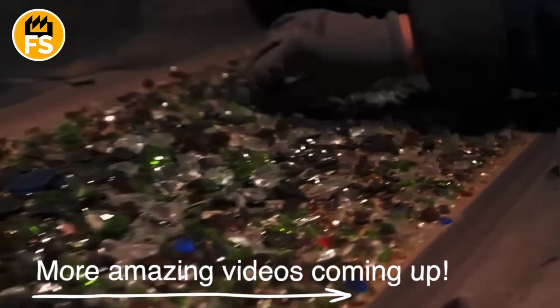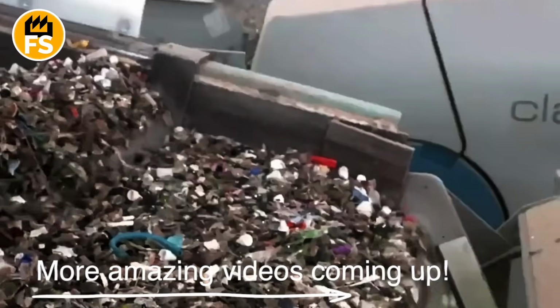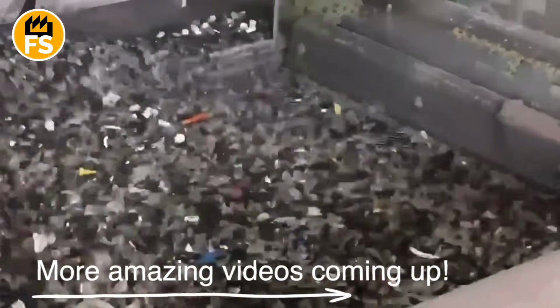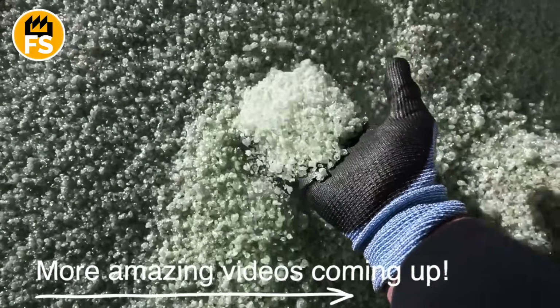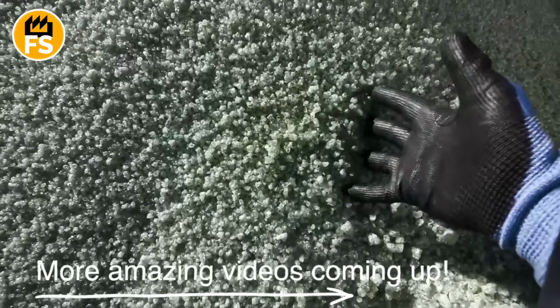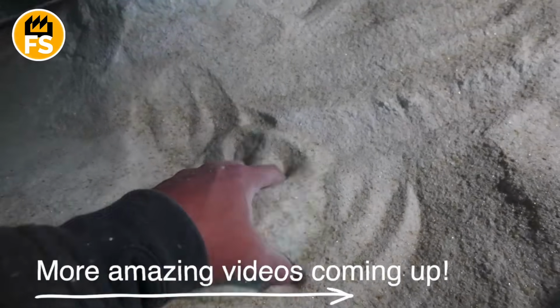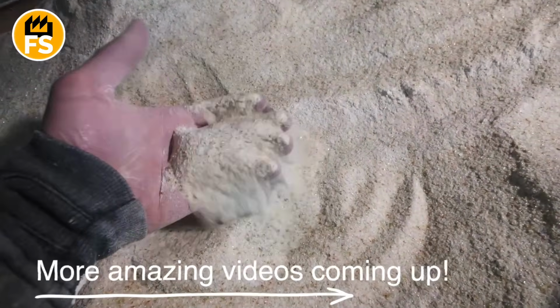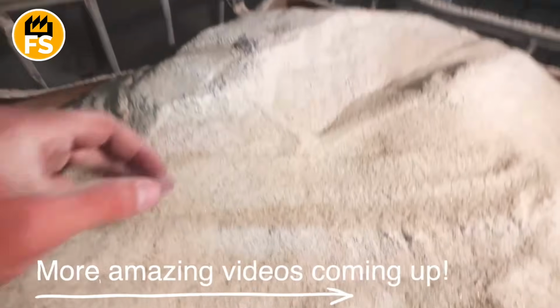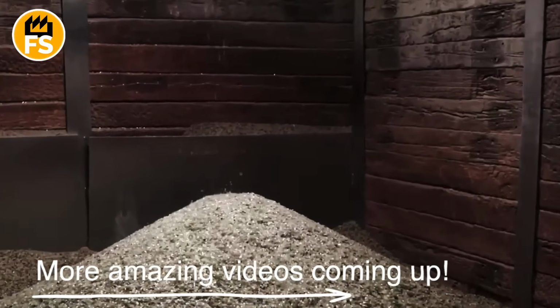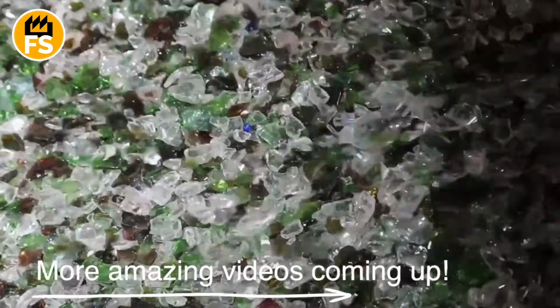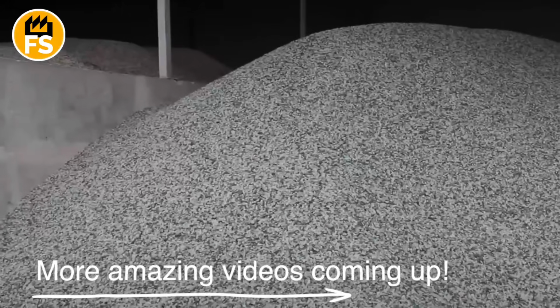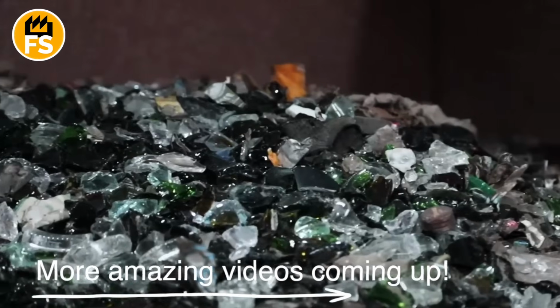Glass recycling has significant environmental benefits as it is energy efficient. The use of recycled glass, cullet, allows for reducing energy consumption for the production of new products, as melting cullet requires a lower temperature than melting raw material. Researchers on this issue indicate a 3% reduction in energy consumption. This also reduces the amount of waste in landfills.